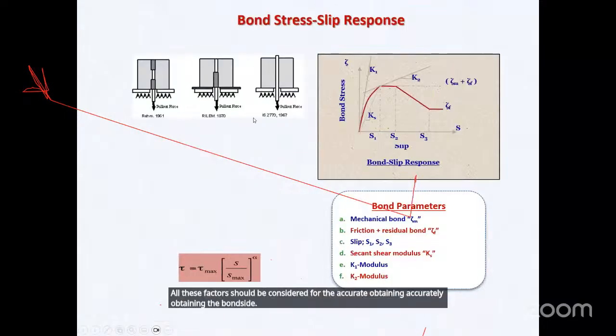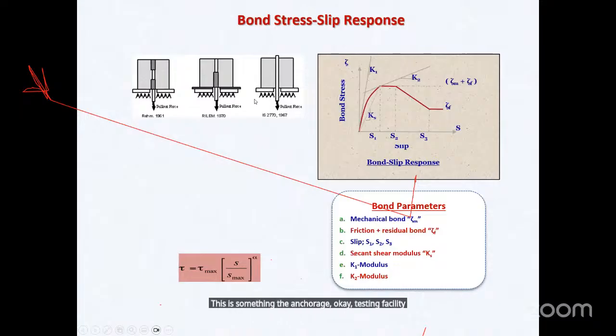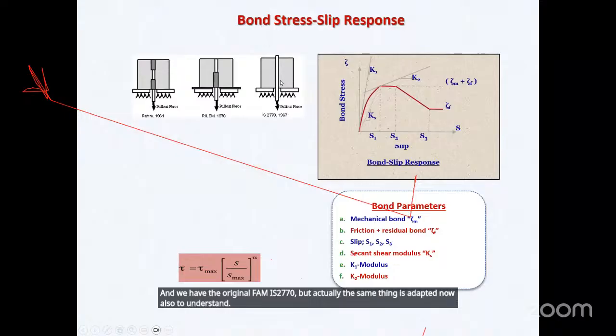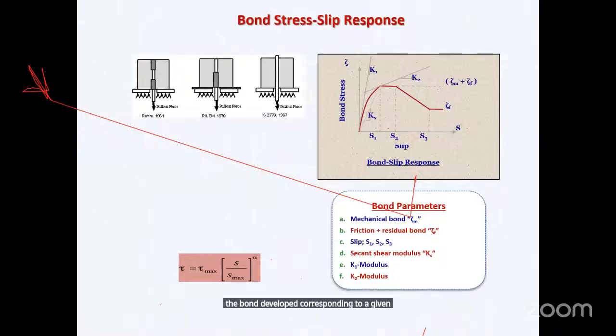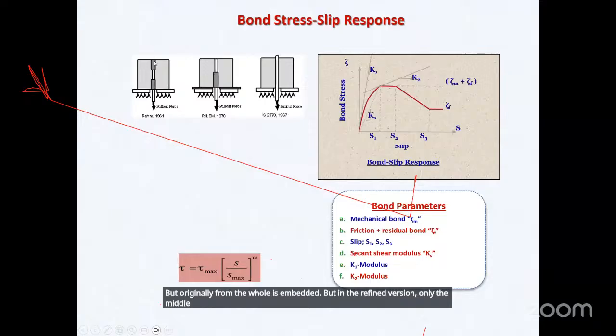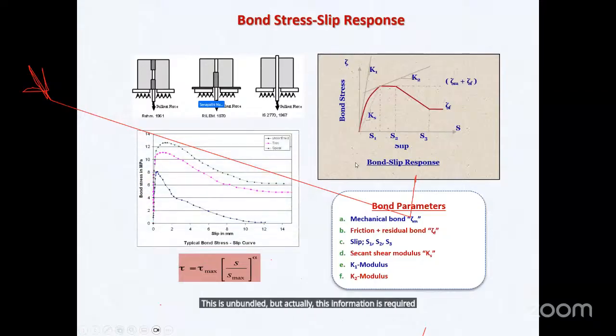This is the anchorage testing facility, the test setup, and we have the original form in IS 2770. The same thing is adopted now also to understand the bond developed corresponding to a given slip, that is, displacement of the rebar with reference to the concrete surface. Due to some reasons, this part is unbonded and only this part is bonded. In the original form the whole bar is embedded, but in the refined version only the middle part is bonded. This is unbonded, this is unbonded. This information is required for us to use these bond parameters.